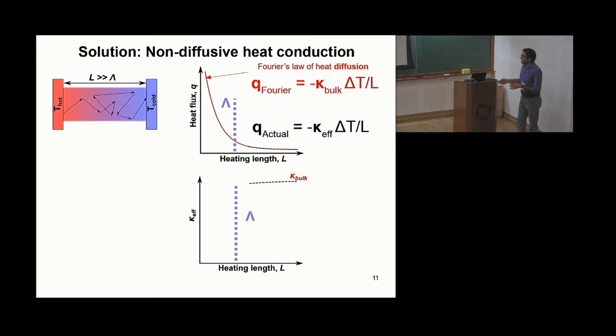So I like to explain that through a simplistic model. Let's take a material where all phonons have a single mean free path for simplicity. Here I am showing a process where heat is conducted from a hot to a cold end through a diffusion process, because L, the distance between the hot and cold ends, is much longer than any mean free path. So phonons can undergo several collisions before they go from hot to cold end. It's a diffusion process.